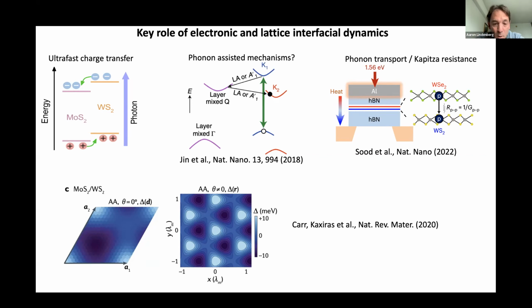But it's also quite well known now that even that picture breaks down in these systems, that there are significant reconstructions within the two-dimensional layers of these structures. I'm showing on the bottom here theoretical calculations from Efthimios Kaxiras's group at Harvard, showing the displacement fields and the variation in the band structure that occurs when you create a MoS2/WS2 junction. So these things are by no means rigid blocks. They're heterogeneous. This is all connected with the moiré properties of these materials.